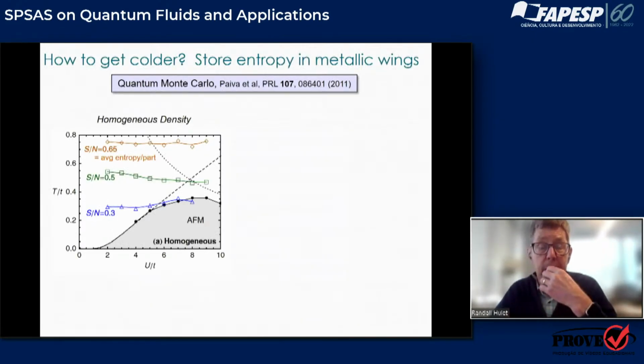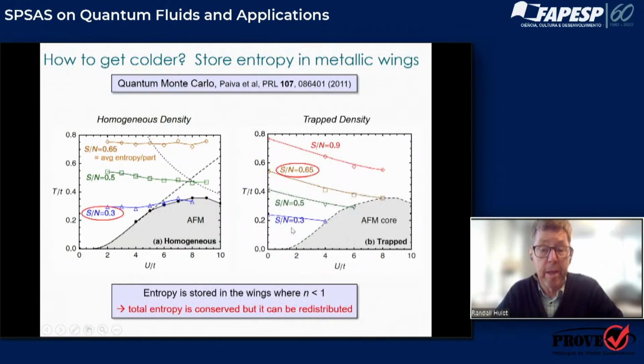So how do we get colder? Well, Teresa's work from a decade ago kind of shows this. Remember the graph I showed earlier, in the homogeneous case where the density is homogeneous, and you needed to get the entropies below 0.3 per particle. But if you take advantage of inhomogeneity, then the peak region and the Mott plateau gives you a way of minimizing entropy locally, and all the excess entropy resides in the wings of the distribution. So this is the case where the atoms are trapped in a harmonic potential. And now instead of 0.3, we only require 0.65.